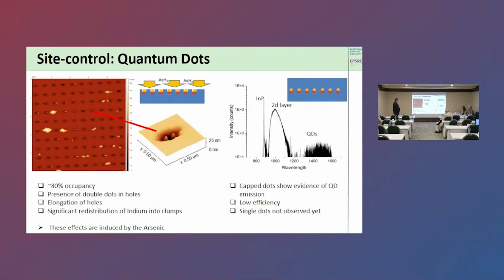Also, the dots form in the middle of the hole rather than on the edge. So actually the presence of arsenic causes significant redistribution of the indium. We get mass transport of this process, and we've seen this in the random dots as well. And so actually we go from droplets around the edge to dots in the middle.